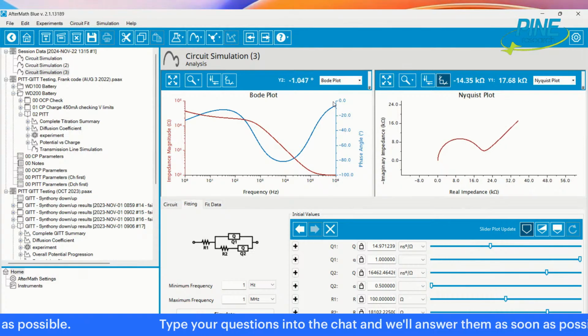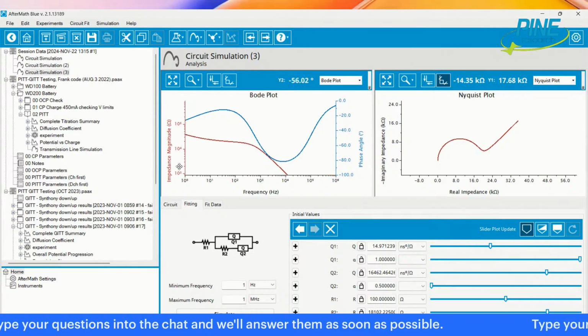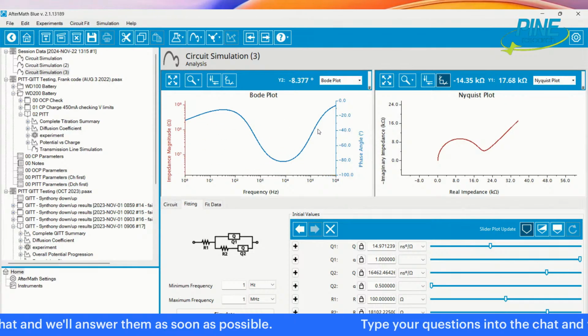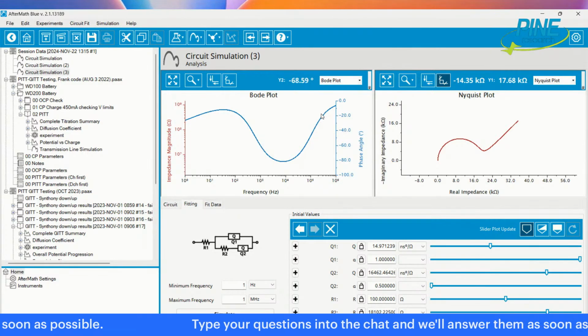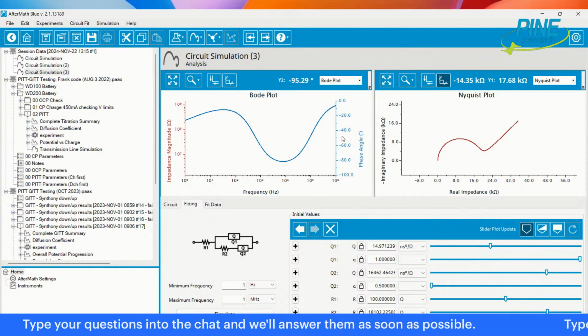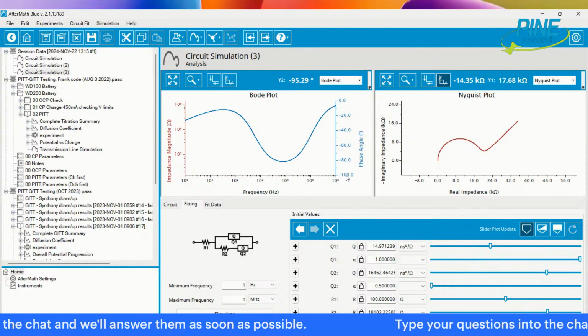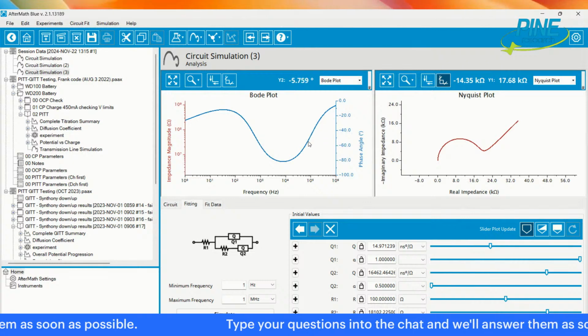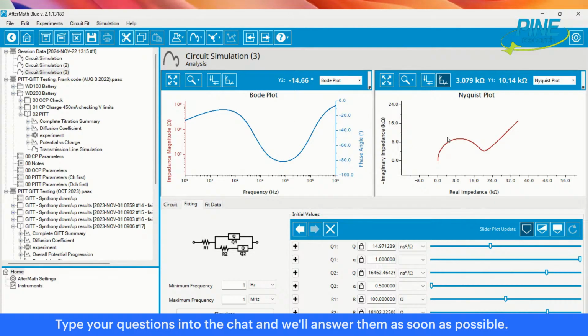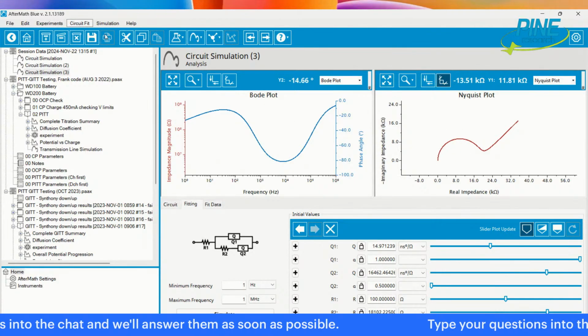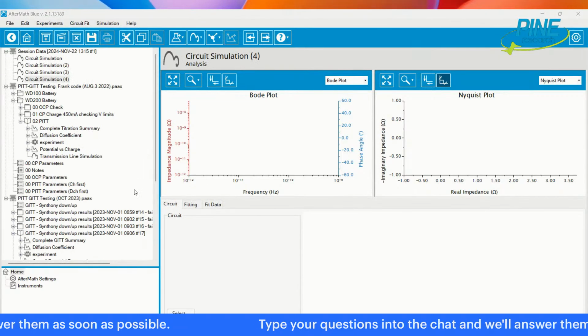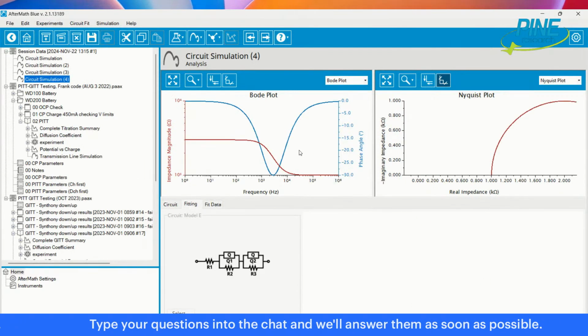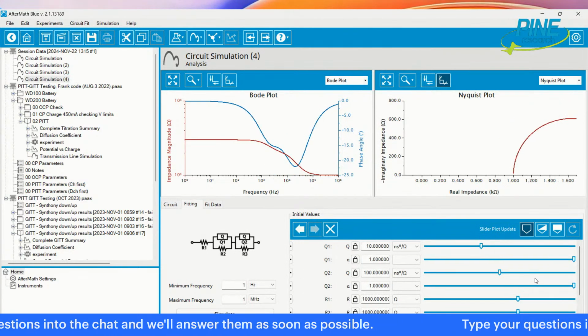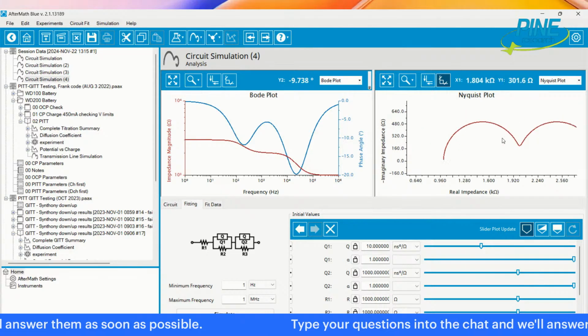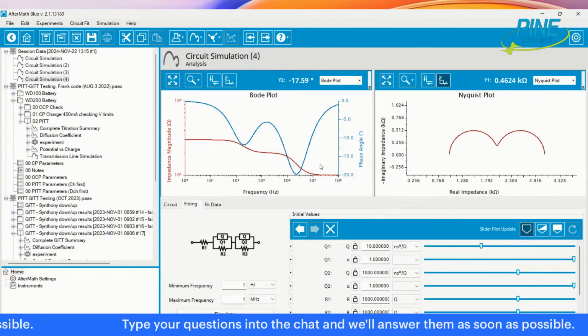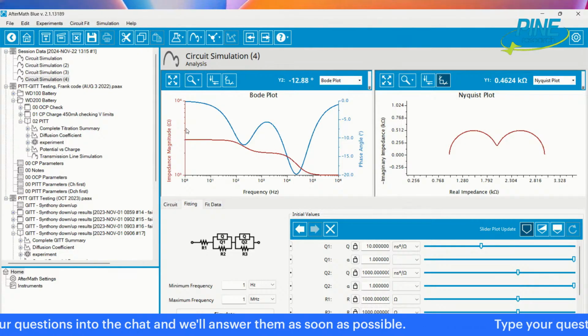On the Bode plot, mainly what you're looking for in the first case, on the phase angle, is the peaks, so to speak. The peaks go down if your phase angle plot is made properly, with negative phase angles going down. You see this one big peak, which correlates to a semicircle. If you have two semicircles, two RCs, you should get two peaks on the Bode plot when I make these different values. So you see two peaks, two semicircles. The peaks on the Bode plot correlate with the semicircles. That's the first, on the phase angle plot.